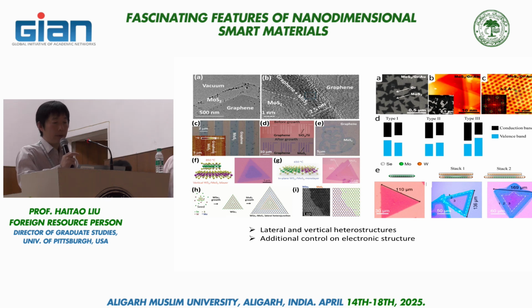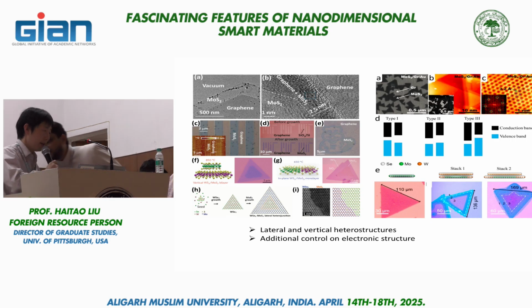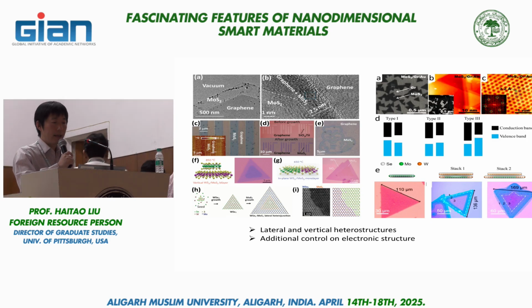You could have a so-called type 2 where you have this staggered band gap, and that is a good combination for charge separation. You can create an exciton, but one charge goes to one material, and the other charge goes to another material. So solar cells come to mind in this kind of combination. But regardless, this is a very versatile technique, and it can give you very useful control of electronic structure and can be useful in particular nanoelectronic applications.